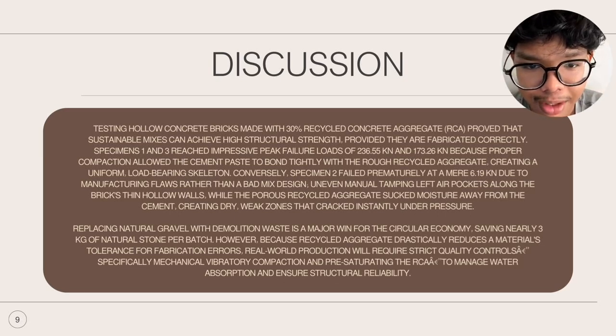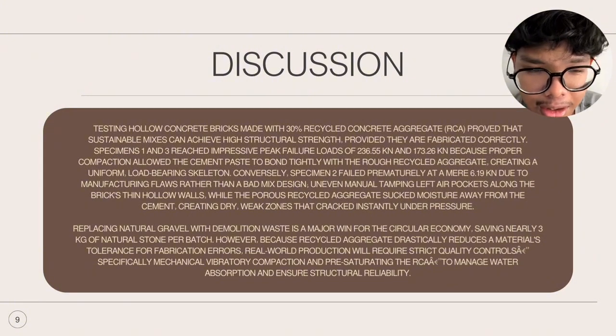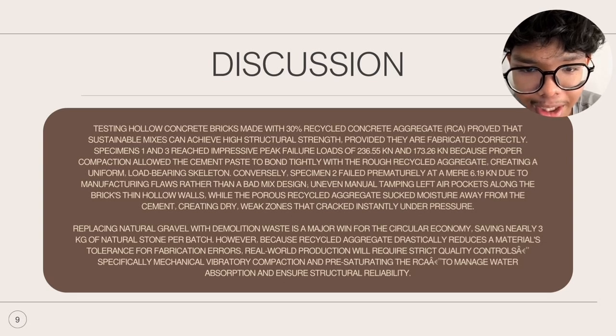bad mix design. Uneven manual tamping left air pockets along the bricks' hollow walls, while the porous recycled aggregate sucked moisture away from the cement, creating dry, weak zones that crack instantly under pressure. So replacing natural gravel with demolition waste is a major win for the circular economy, saving nearly 3 kilograms of natural stone per batch. However, because recycled aggregate drastically reduces a material's tolerance for fabrication errors, real-world production